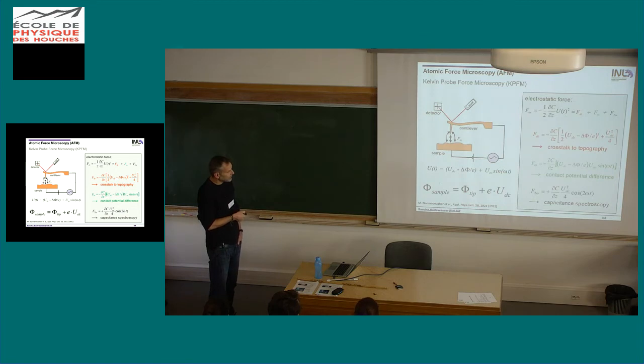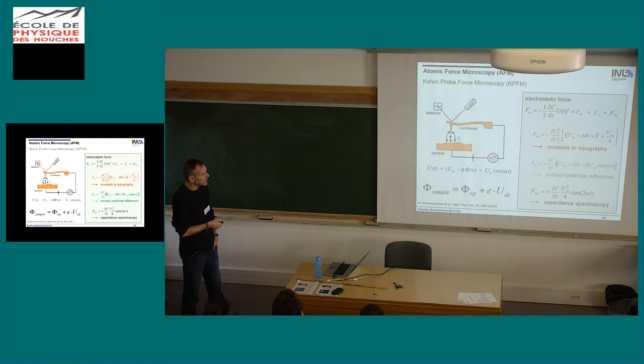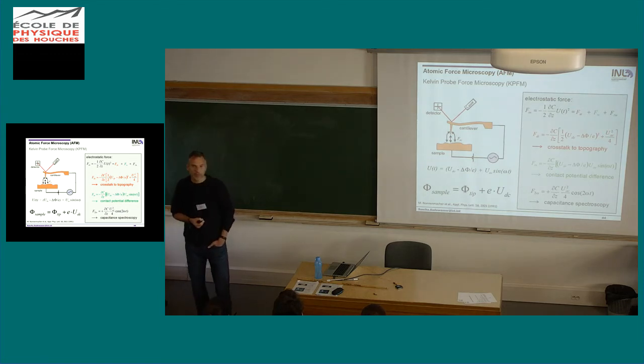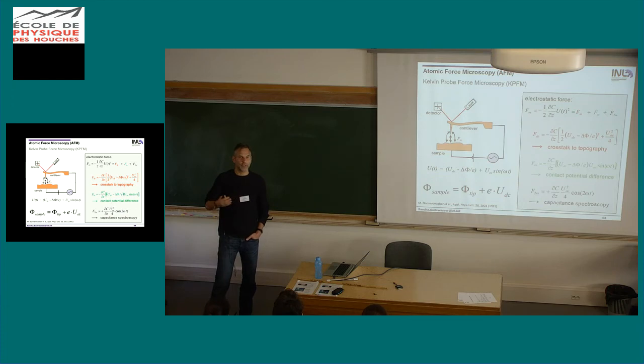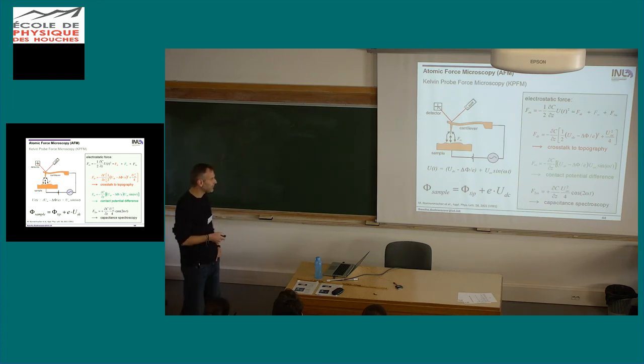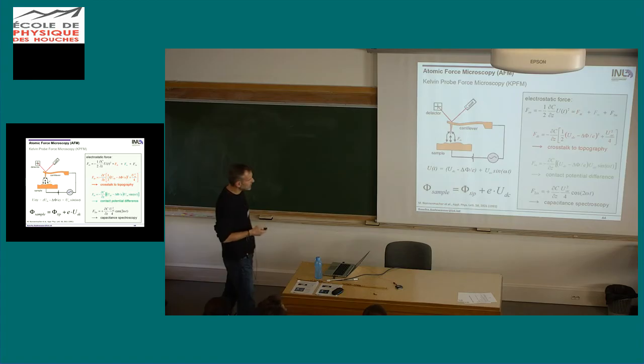Contact potential difference was the difference between sample and tip work function. So if we write this as the work function of the sample, then that equals the work function of the tip plus the DC bias that we apply. You can define this whichever way you want. So it could also be the opposite. But what we do in our lab, we always use it in such a way that the contact potential difference has the same direction as the work function of the sample. So if the contact potential difference increases, then the work function increases. But this is in principle arbitrary. So this is how it works.